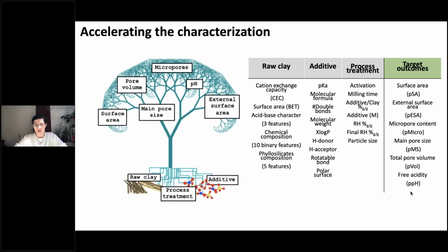Here I disclose the individual descriptors. Since the raw clay minerals as natural porous materials are hard to be modeled, the 20 descriptors were experimentally obtained, while the additive were depicted by 14 descriptors obtained by PubChem repository. Then the process treatment, 7 descriptors, identify the different material preparation which can be experimentally made.